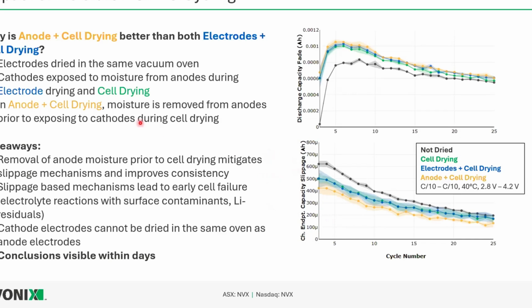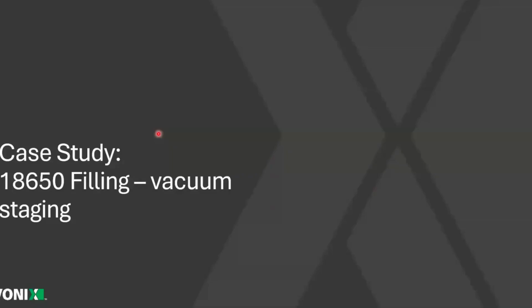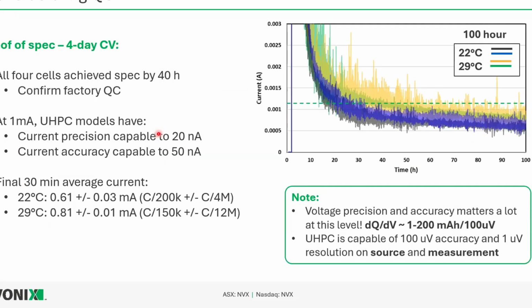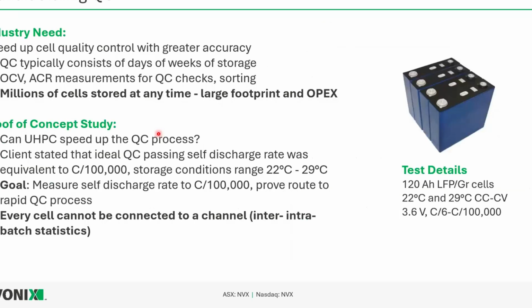last question, what's the limit of cell size or C rate where the effects start to deviate from normal cycling test results? Again, that kind of depends on the tests that are being done. But in this specific test, I'm doing this on a 120 amp hour LFP graphite cell. The max I can cycle this cell at with our current systems, which go up to 20 amps, is C/6, but that's still plenty relevant to do these QC-based tests, get a cell up to a voltage range, and then start going into that CV down to these really low currents.